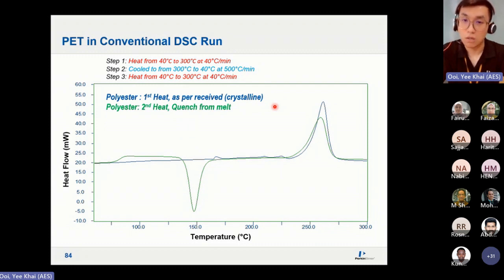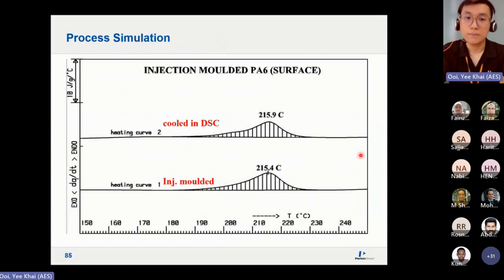Okay, this is not wrong. This is just how you prep your sample or how you run your materials. And usually this is only for semi-crystalline material. If the material is fully amorphous, only Tg. If it's fully crystalline, it's going to be a melting peak and also a crystallization peak. So you can use this to simulate the processing condition.